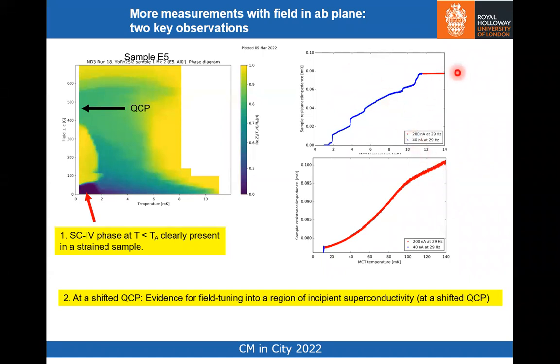So what this is showing you is, and sorry, it's so small, the zero field transition. So it's occurring initially at 11 millikelvin, and it's meandering down to zero over a wide temperature range, but it reaches zero at about 1.5 millikelvin. So here is a color plot of the sample resistance over field temperature phase space. Dark blue refers to the well superconducting regime, and you can see this is the SC4 phase at temperatures below 1.5 millikelvin. It's present even in this strained sample, in this bottom left-hand corner, at low temperatures below 1.5 millikelvin and low magnetic fields.